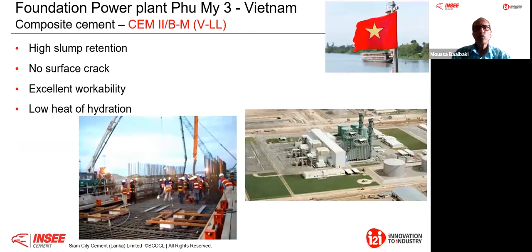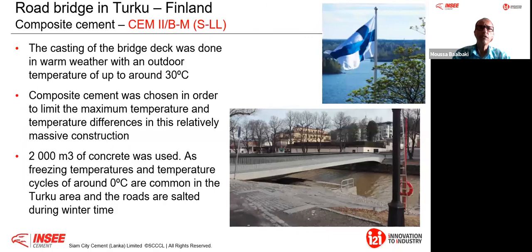In Vietnam, CEM2BVL, again the same. It's a fly ash and limestone cement. It is used for the foundation of a power plant, for high slump retention requirement, no surface cracks, excellent workability, pumpability, and low heat of hydration. This is in Finland. I like to present this example where you see how composite cement was used. This is, for example, an SLL, a slag and limestone cement. That is the product we will produce in Ruhunu, in Galle.